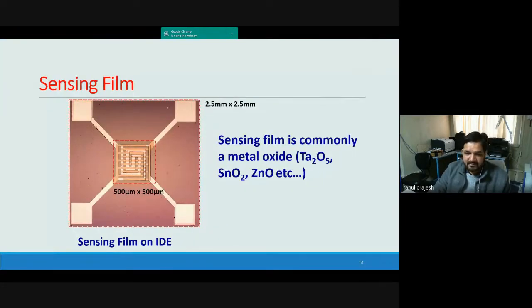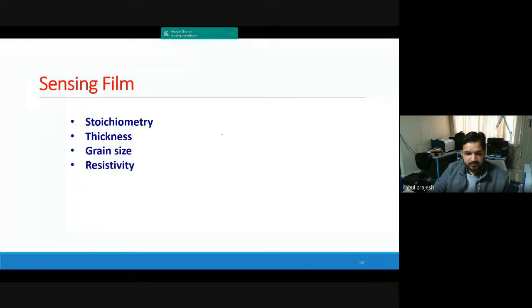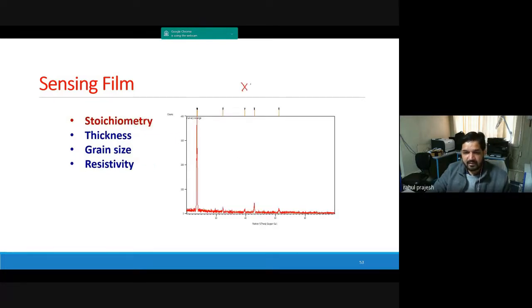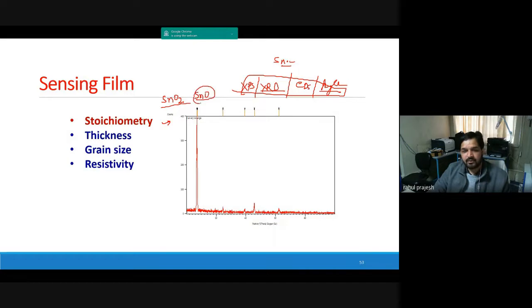Now comes the sensing film. What are the important parameters that I will discuss? One is the stoichiometry. Then what should be the thickness? What should be the grain size? Why is it important? And what is the resistivity? Why is it important? For stoichiometry, you can take the help of XPS. XRD will also tell you which phase is present. EDX and Auger electron spectroscopy you can also do. So there are different techniques to check the stoichiometry of a particular material. Are you getting the correct stoichiometry or not? For example, you want to make SnO2. Are you able to get SnO2 or is it SnO? You need to have the correct composition, then only you'll get the best sensitivity.